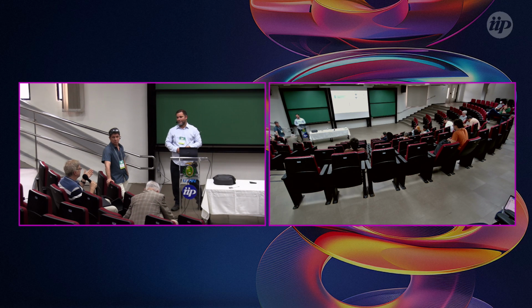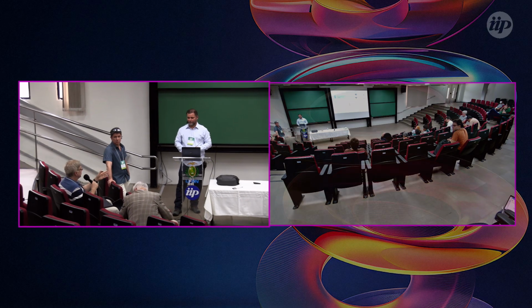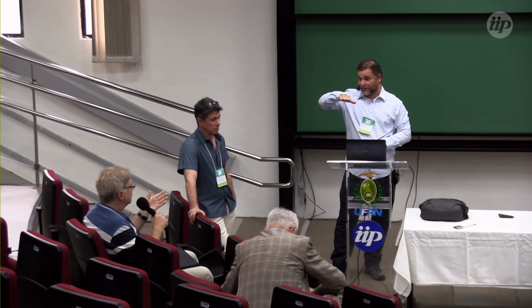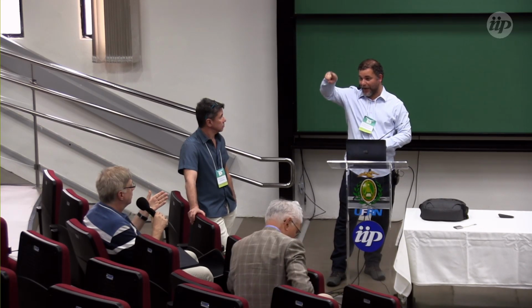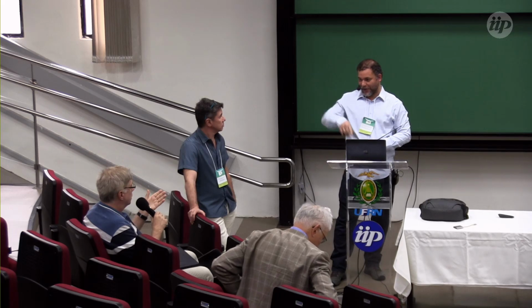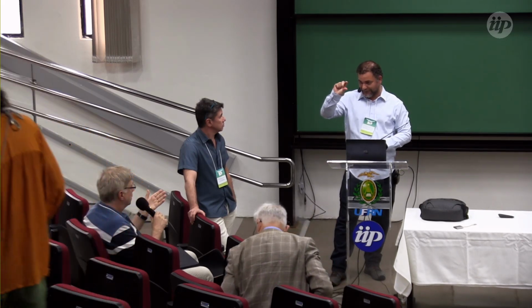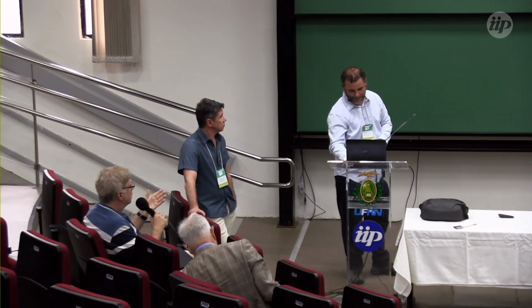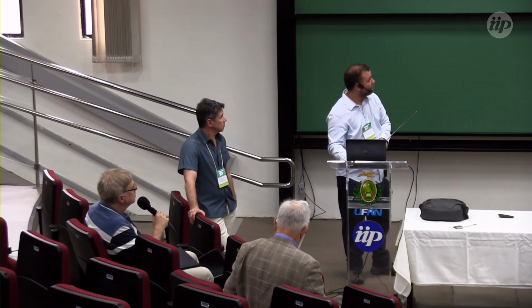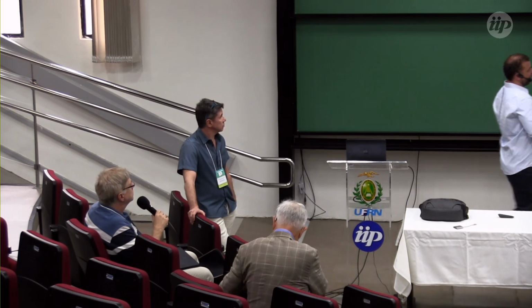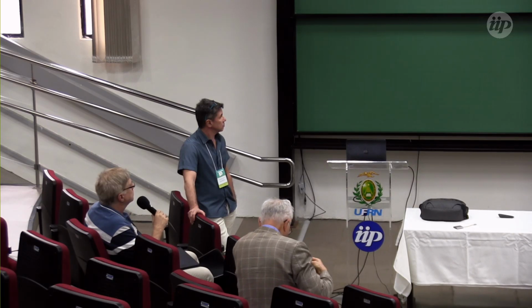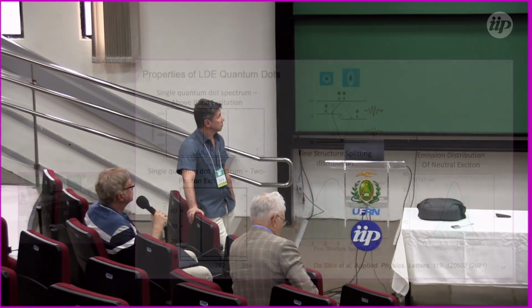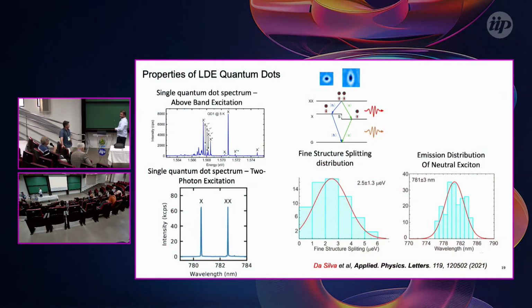When you mention the fine structure, what this means is that you have some structure in the line, no? It's the splitting of the neutral exciton level. If you do a polarization map as a function of energy, you will see this small splitting here, which is what we call the fine structure splitting of the neutral exciton.